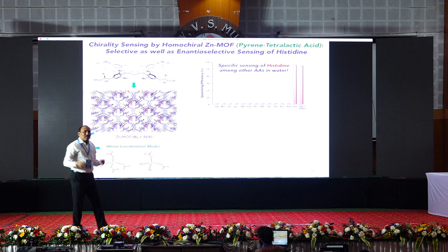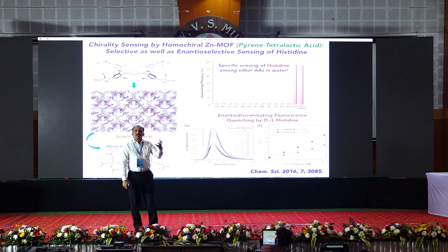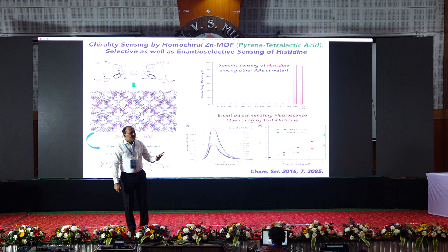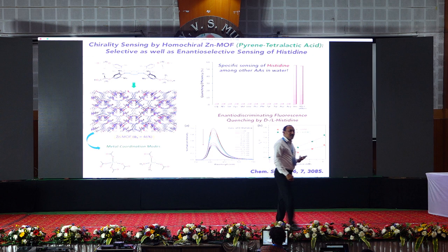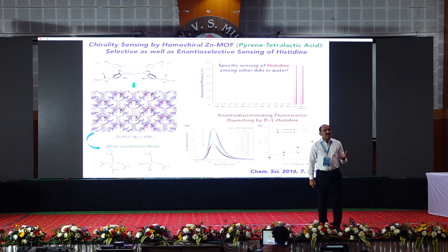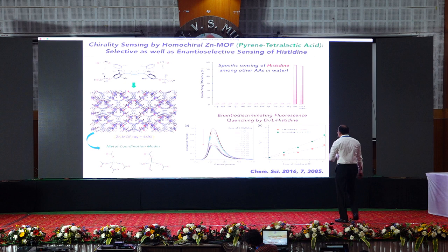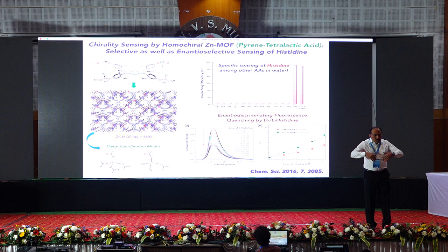Why, we can talk about outside, but suffice it to say that you have built a material which typically functions like an enzyme, which selectively captures only histidine and senses if histidine is there or not by a diminution in the fluorescence intensity that you see. Not only that, of course, when you speak of histidine, you have D or L stereoisomers, and because I said that the material is homochiral, can we differentiate between the D and L? In fact, you can differentiate between the D and L, with L being sensed poorly when compared to D, if you look at the Stern-Volmer constants. That is about 3D. I just want to give a glimpse into how you build materials based on molecules.